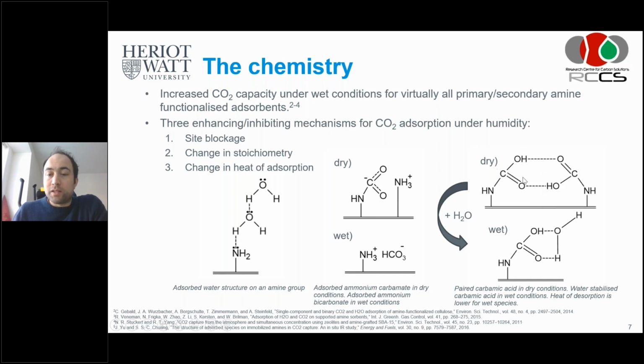But carbamic acid isn't necessarily stable, so it needs to be stabilized by some other molecule. For instance, by a carbamic acid molecule that is linked to an amino group next to the site where you're absorbing your CO2. But under wet conditions, it can also be stabilized simply by a water molecule. And that has an influence on the heat of adsorption, because the heat of adsorption of the paired carbamic acid is higher than the heat of adsorption when the carbamic acid is stabilized by a water molecule.